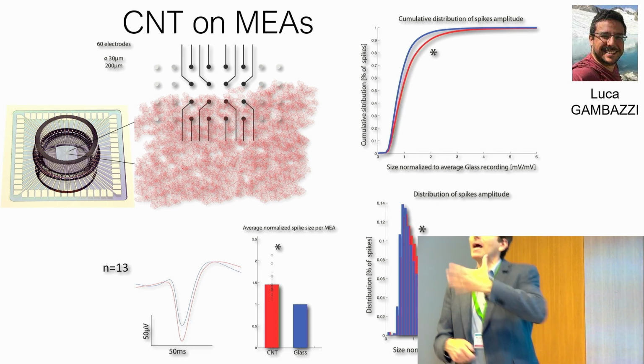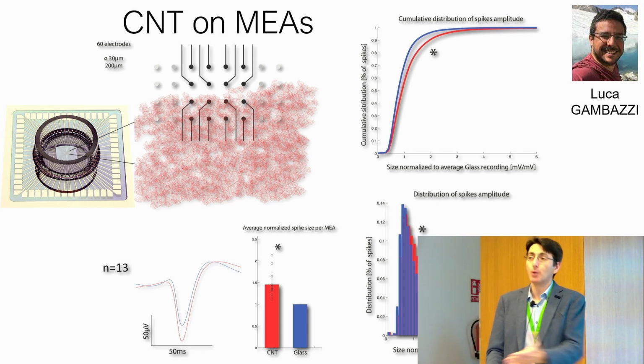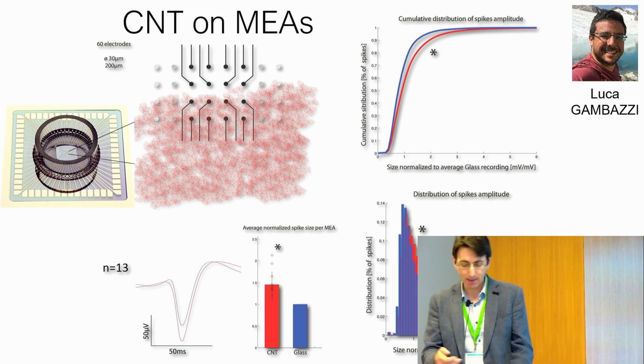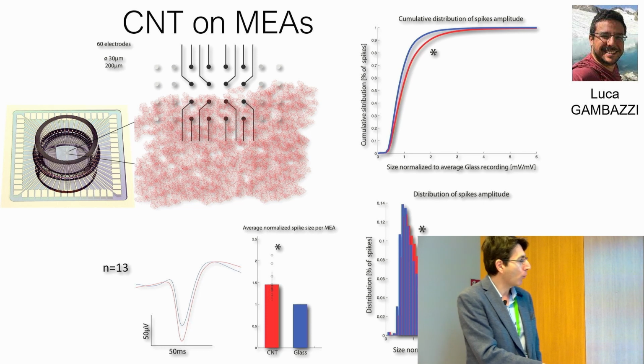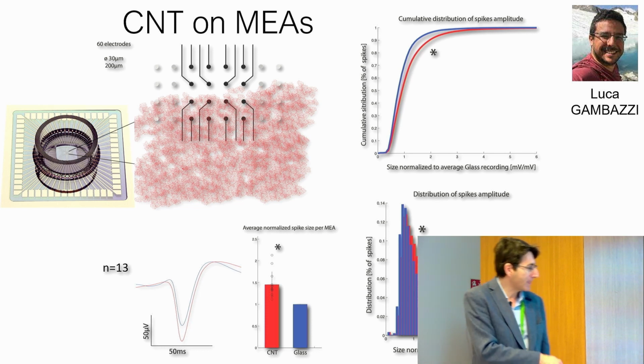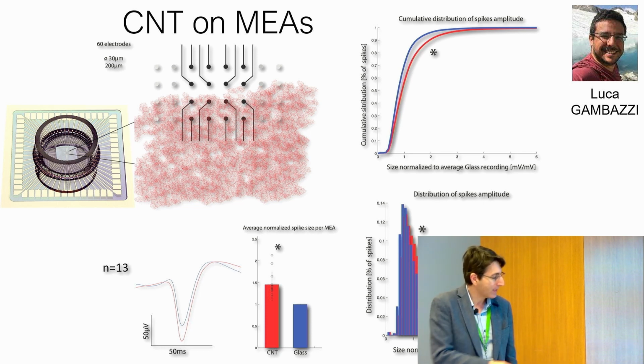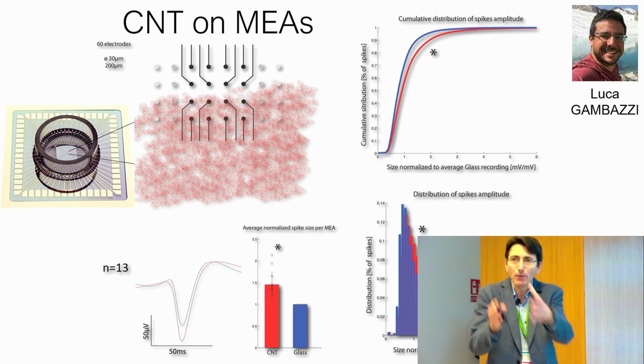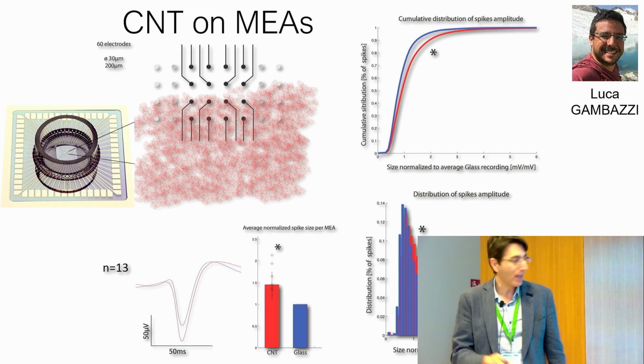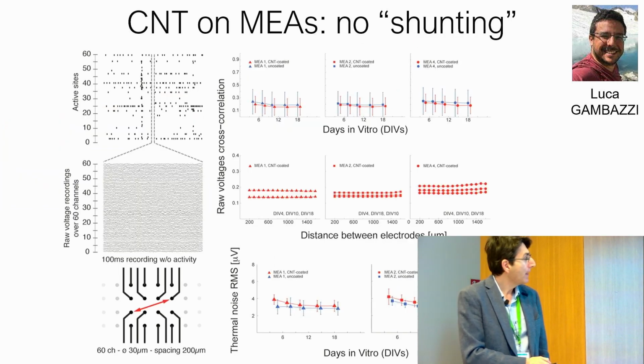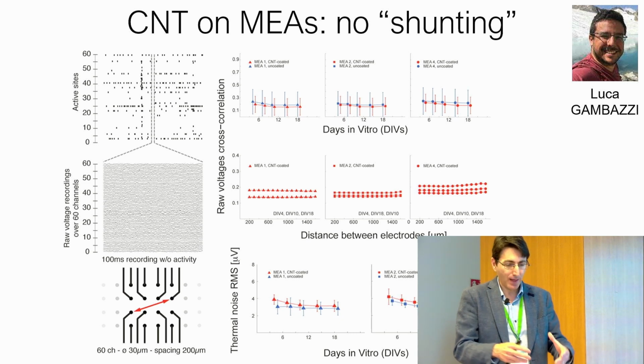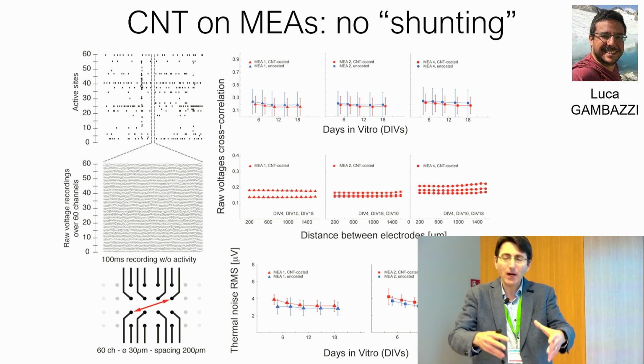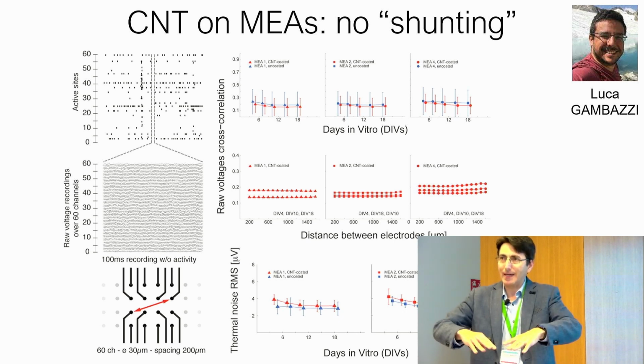They were larger. So you get better signals because you have better impedance in this way. And this is another way to describe the same thing. This is the representative picture out of 13 of these experiments, 13 microelectrode arrays. And to our surprise, the fact that you put a meshwork of carbon nanotubes did not shortcut the electrodes.